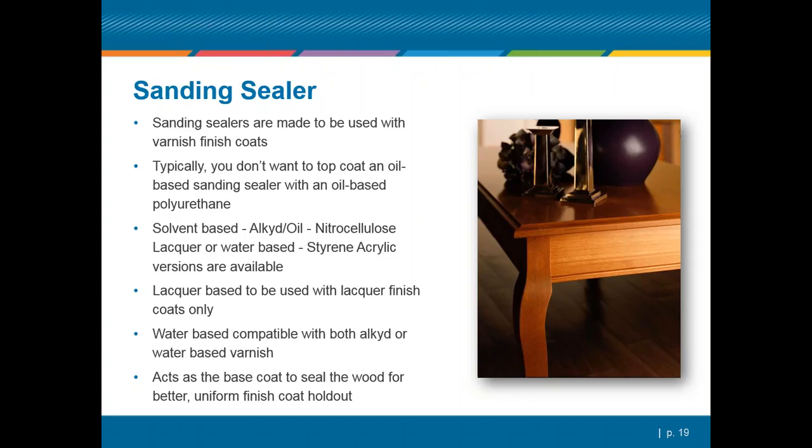You can put a sanding sealer down on the wood, and the reason we use a sanding sealer as a seal coat over new, well-prepared wood, and then sand that sanding sealer, and that's part of the benefit of these things, is they sand very nicely, and they powder up nice and wipe off nice, so that whenever you come back with a varnish finish over the top of them, you have a very smooth, well-sealed surface to put your varnish on top of.